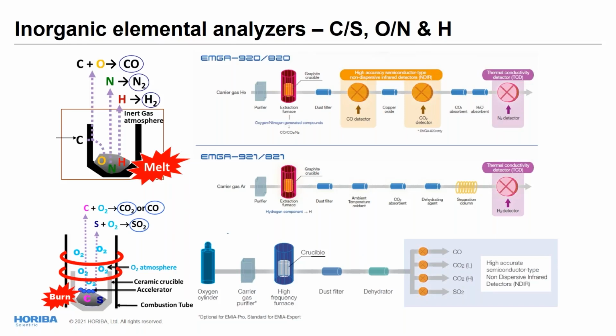For the determination of oxygen, nitrogen, and hydrogen, the sample is introduced into a graphite crucible. This crucible is placed into an impulse furnace under a flow of inert gas. By temperature increase, we are going to produce gases. Nitrogen and hydrogen will produce nitrogen gas and hydrogen gas, while the oxygen will react with the graphite of the crucible to form carbon oxide. All these gases will flow into the system. The oxygen will be detected by CO and CO2 NDIR detector. NDIR stands for non-dispersive infrared, while the nitrogen will be measured using a TCD detector, thermal conductivity detector.